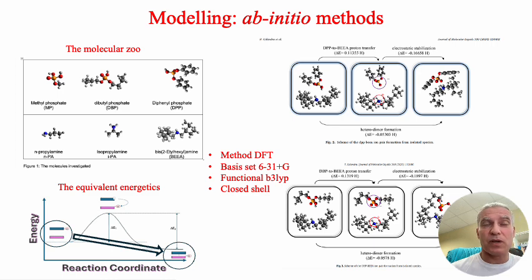By ab initio calculations, we found that there is a direct hop from this state to the other one. So this is just a scheme to understand all the contributions involved, but in reality, this mechanism is, we say, concerted. They are not separate in time, but they happen all together, simultaneously.